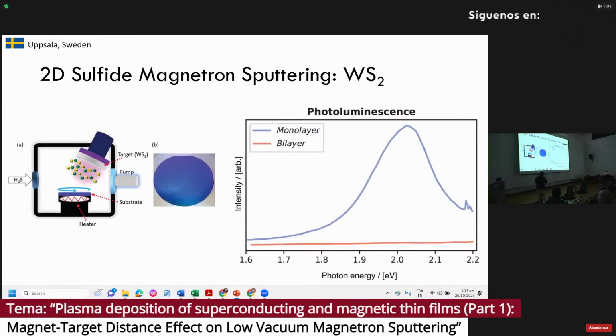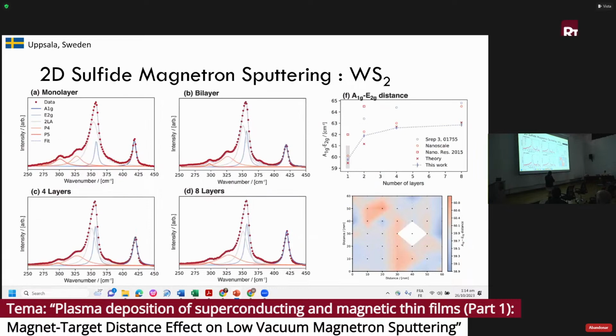And this one was done during my postdoc at Uppsala University, where we deposited a single layer of tungsten disulfide onto this 4-inch silicon wafer. The reason that we say it's single layer is because we have seen a photoluminescence of this material, and we also tried a Raman mapping where we monitor the distance of the A1g and E2g peaks, and this gray zone is actually covering these values here. So we have this single layer of our material.